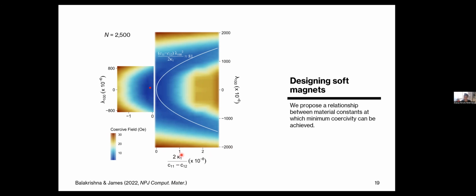So if I take an anisotropy constant, which is about 1,000 joules per meter cube over here, and I make the magnetostriction constant, let's say 0, I have a coercive force of about 15 oersteds or so. And so the region that you see in blue is the region that offers the smallest coercive field or the smallest coercivity, or these are the magnets that are softest with the smallest hysteresis width. And what you see here is a red dot that corresponds to that of a Permalloy composition, a value where the anisotropy is close to 0, but not exactly 0. And today's alloy development strategy is focused on making this anisotropy constant close to 0. And what our calculation in fact showed is, well, you can have a soft magnet with a non-zero anisotropy constant, say, for example, along this value over here. But if you tune your magnetostriction constant to suitable values, which is about 1,000 microstrains over here, you can actually get an alloy composition or a new magnetic alloy, which has coercive forces comparable to that of a Permalloy or soft magnets with kappa 1 close to 0.